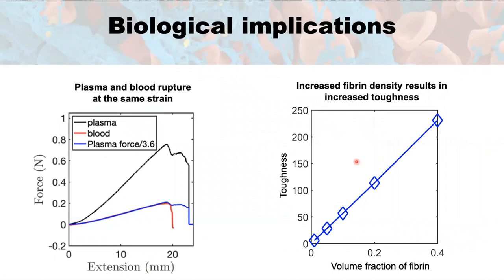Now, importantly, we can turn back and think about how this model can then inform some biological implications and some of the findings that were presented in this manuscript. So importantly, we're focusing on the plasma component, but of course there are blood cells that are present in the blood typically, right? And so we were able to do some preliminary experiments and some modeling where we see the plasma curves like the one that I presented here shown in black. And we did curves of the rupture process on whole blood, which can be seen experimentally in red.